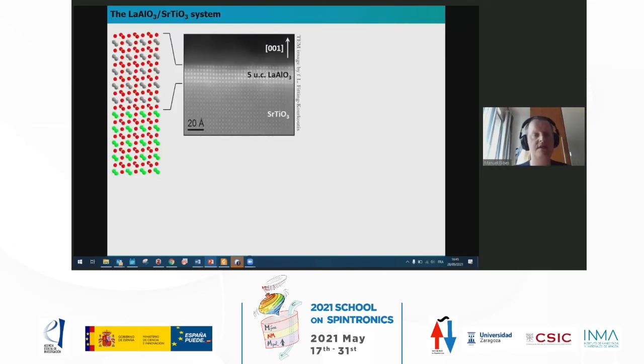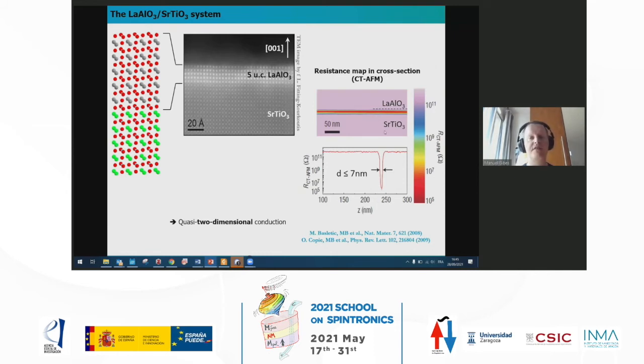So oxide 2DEGs, probably you all know about this. This is the most paradigmatic system, the LAO/STO system. And if you don't know about that, this was a very arresting result from 2004 by Harold Hwang when he was in Japan. Basically, he grew a thin layer of lanthanum aluminate on top of strontium titanate. And although these two materials individually are very good insulators, when one is grown on top of the other, you get a conductive behavior. Basically, you have a two-dimensional electron gas that appears at the interface. A few years later, in 2007, we actually imaged the two-dimensional electron gas.